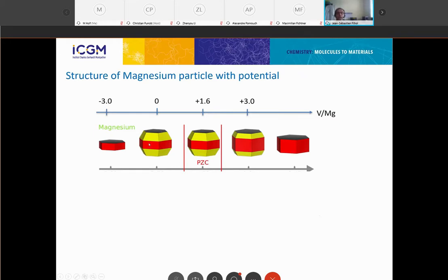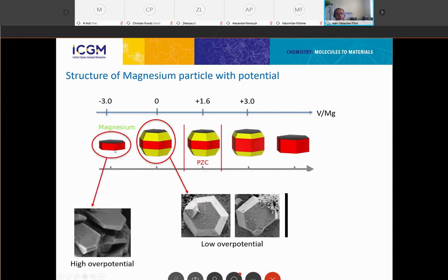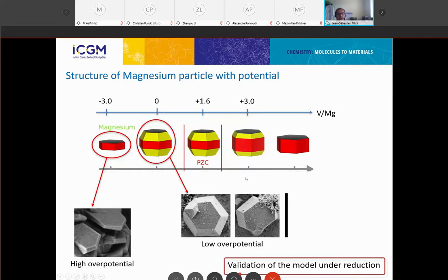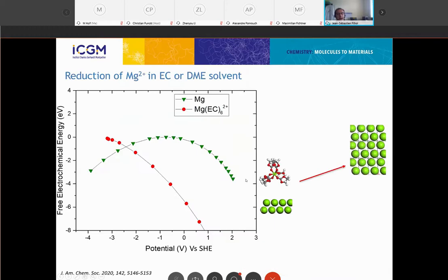The structure corresponding to the zero charge will be quite similar. It will be mostly a bulky octahedra. And when you go to very high overpotential, you get some kind of hexagonal platelets, which is in correspondence with what is found experimentally. So things seem to be fine also for magnesium as for lithium. Now, the first step of our study was investigating the simplest reaction, that was the transformation of magnesium 2+ into magnesium metal at the interface. We did a study on the different solvation spheres, and we find some kind of always octahedra over the magnesium.